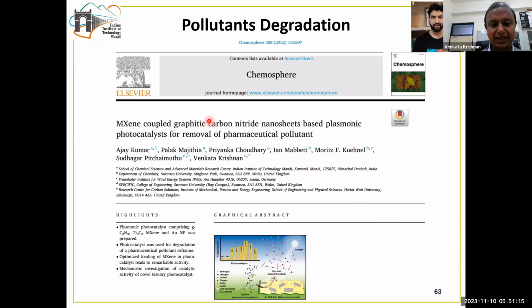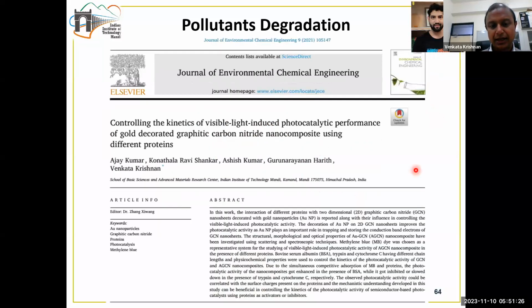We have coupled this MXene with graphitic carbon nitride and used it as a plasmonic photocatalyst for the removal of pharmaceutical pollutants, obviously after decorating them with gold nanoparticles. And in another work, we again took the gold-decorated graphitic carbon nitride nanocomposites and used them for controlling the kinetics of the visible light induced photocatalytic activity, wherein we coupled them with different proteins, and some of the proteins enhance the kinetics and some of them decelerate the process.